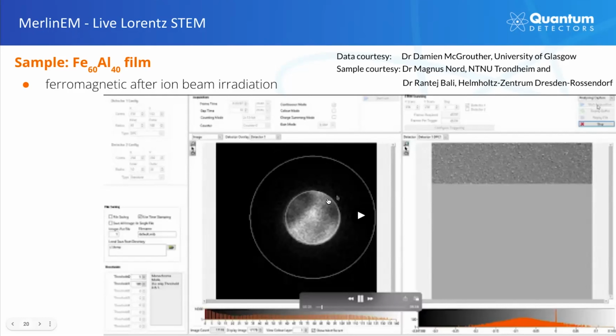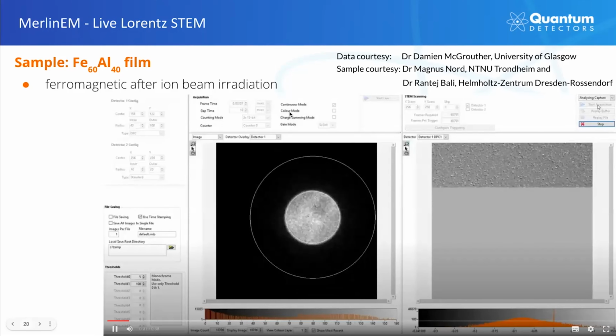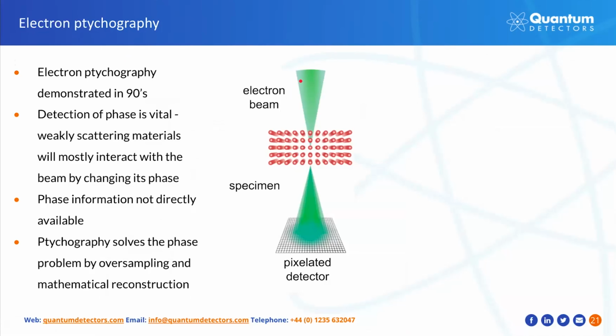In any case, the differential phase contrast is related to our next application, ptychography. The main difference between the two methods is that whereas differential phase contrast measures the gradient of the phase of the sample, electron ptychography is used to measure the phase directly. Electron ptychography was developed and experimentally demonstrated in the 90s, but until the arrival of fast pixelated detectors, it was limited by the practicality of the experiment. The motivation of electron ptychography is to recover the phase of the sample.